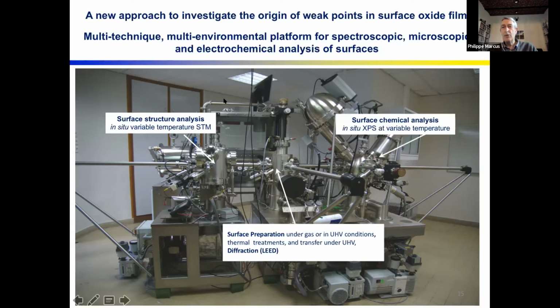In another part, we can do in situ XPS, that is, we can do XPS in the presence of gas, and we can make real-time measurements of oxidation in a gas environment. And finally, we can transfer the samples inside this equipment to a glove box in which we can do some analysis of the solid-liquid interface, and there is an electrochemical scanning tunneling microscope. So it's a sort of material science or surface science lab in which we can do surface preparation, heat treatments, exposures to gas and liquids, and analyze the surface chemically and structurally without exposing the surface to air.